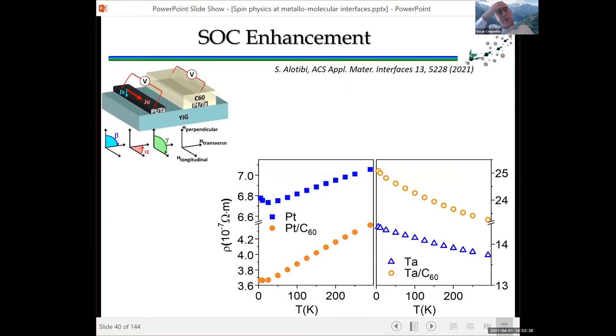The first thing that we observe is that when we put C60 on top of platinum, we change the resistivity because we form this metallic interface. But surprisingly, if you put the C60 on top of tantalum, the resistivity is increased. If you put it on top of platinum, the resistivity is decreased. And that's also to do with the different slopes in the thermal dependence of the resistivity for both elements.